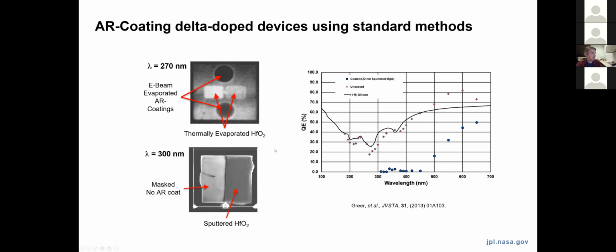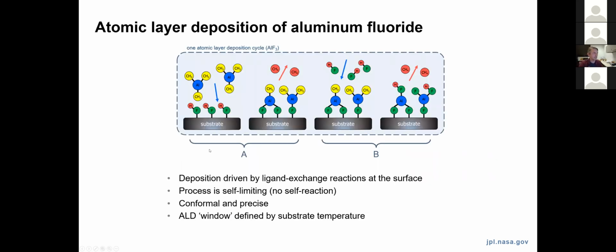And so that led us to options that were a little bit more gentle from sort of the physical perspective. So something like thermal evaporation works. It tends to be a little bit harder to control the uniformity in a thermal evaporation process. But as I'll show in the next few slides, atomic layer deposition emerged as a nice technique for these optical coatings. It's a gentle chemical process that did not degrade the performance that we were expecting of the delta doping.